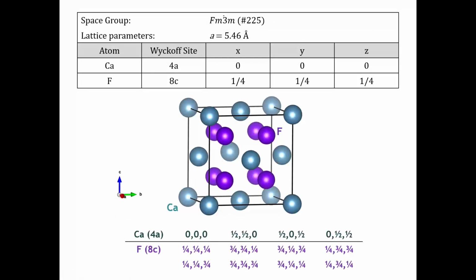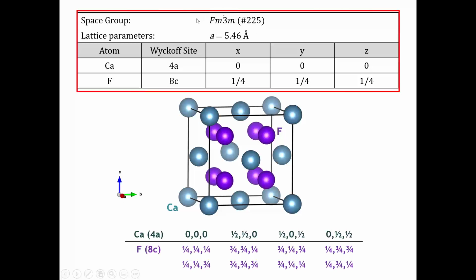Now, if we were to look at the representation of a crystal structure of, let's say, the mineral fluorite, all the information that we need to convey that completely depicts the crystal structure is given in the table above. We have to specify the space group symmetry, here Fm3̄m. We have to specify the dimensions of the unit cell. And since this is a cubic space group, once we specify the length of the edge of the cube, we've given all the information that's needed to specify the unit cell dimensions. And then we have to list each crystallographically independent atom. What do I mean by that?